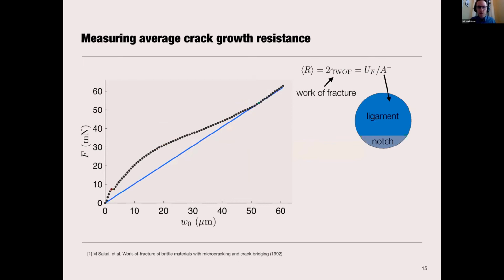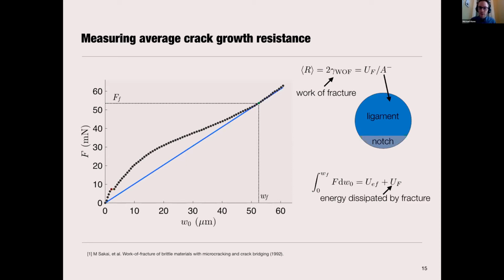So I'll start with how we measured the average crack growth resistance. As I said, average R is twice the work of fracture, which is the total energy dissipated in that fracture process divided by the cross-sectional area of the ligament. We can compute the work of fracture using an incremental energy balance, where on the left-hand side of this equation you have the total extrinsic work done on your system. On the right-hand side, you have some elastic energy, U sub EF, and your energy dissipated by fracture, U sub F. In many cases, the elastic energy is going to be 0.